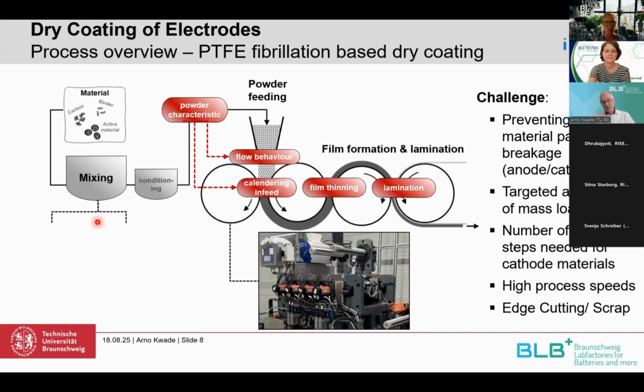And the typical dry coating process today looks like it is shown here. You have a mixing process, then sometimes a conditioning process where you, let's say, decrease, for example, the size of the granules which you produce during the mixing. And then you have the dosing by a powder feeding system. And then you have the film formation, in this case here, what is the most typical case, by a calendering process. We will come to the different processes, mixing, feeding, and film formation later in more detail.